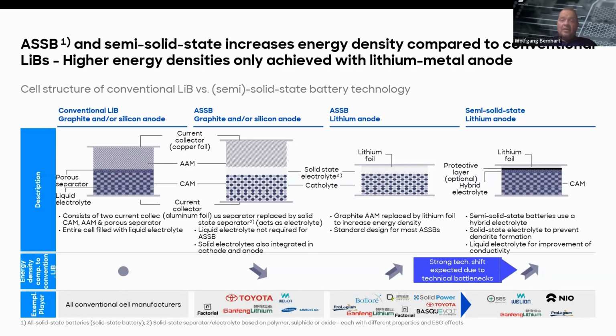So you typically have a lithium foil that can be either a freestanding lithium foil, it can be a lithium that is deposited on a current collector, but metallic lithium, or you have a current collector and actually a lithium as being deposited during the first charging cycle, often or sometimes also referred to as anode-free design. So the anode material, the graphite anode material, is replaced by lithium foil, and that's the standard design, I would say, for most of the all solid state